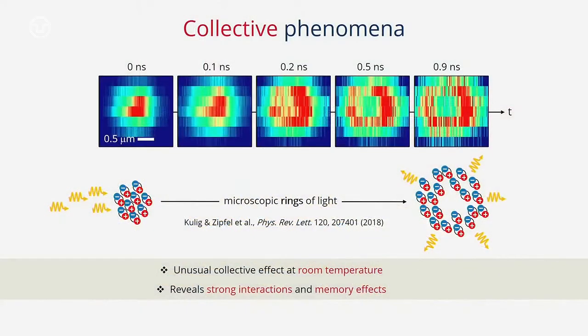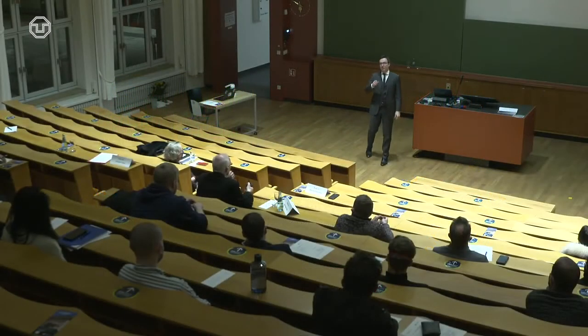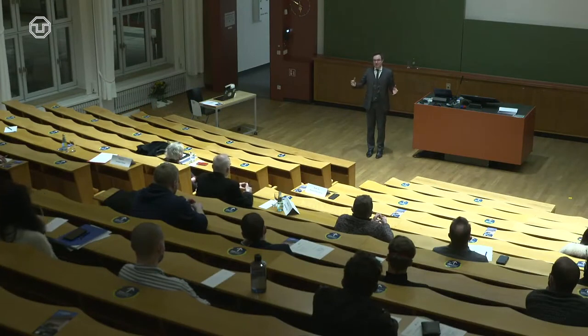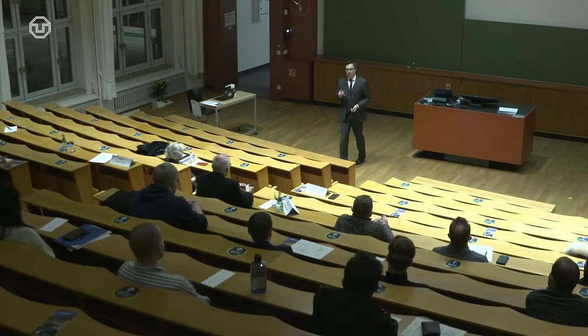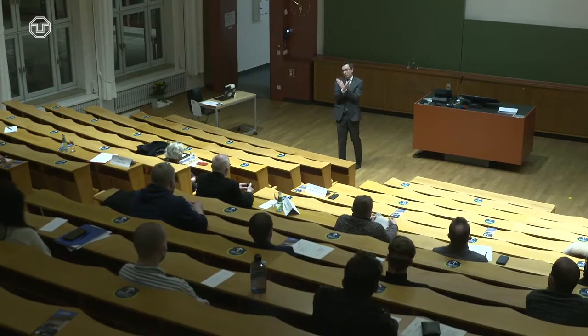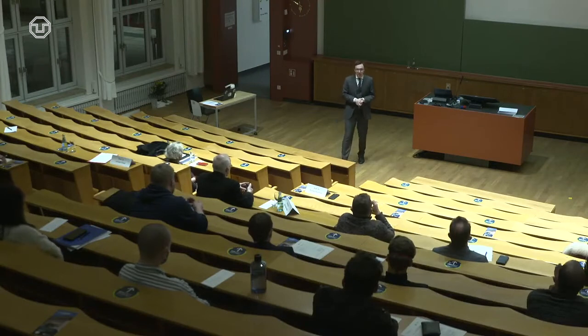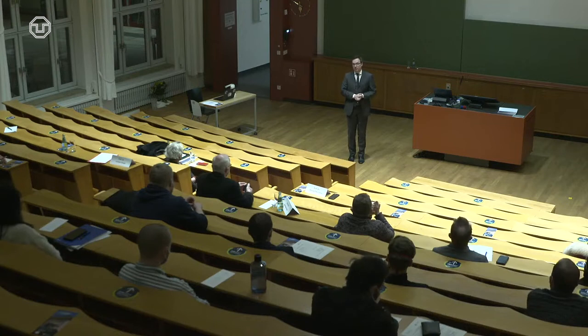Otherwise, you can imagine material where, if you take for example linear dispersion, ballistic propagation in something like graphene, you would expect it just from the dispersion alone. But that's not the case here, which is something you would be able to distinguish because the speed would be different. That's correct. We would need to think that we have a ballistic wave that is just not reconcilable with this scenario. But people propose ideas like this. They calculate band structures that look like this and say that in such a band structure, if your exciton moves, then it should do a ring, not because of many-body interaction, but because of the band structure itself. But here, we are rather convinced that it's not the case, for a variety of reasons.